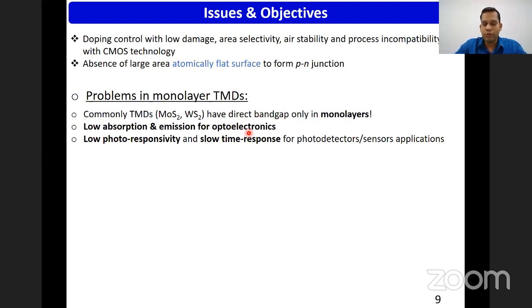But there are also some negative points for monolayer TMDs, because the thickness of this material is atomically thin. So the light absorption is not so strong for application in optoelectronic devices. So that is also one drawback. We need at least some thickness so that the light interaction can occur strongly, so that optical absorption can be higher for a real device application.